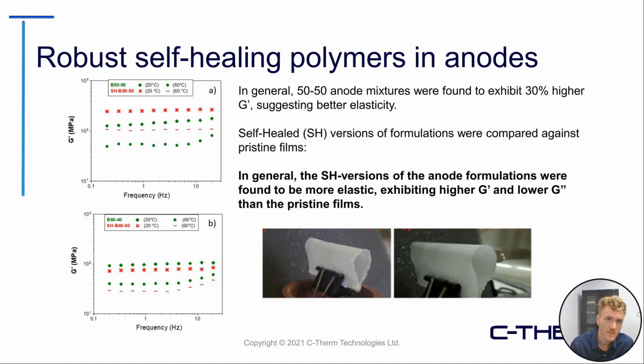And they were able to do some DMA testing by sweeping the frequency and measuring the G prime, or the elastic modulus, during the experimentation. Upon taking some pristine samples of the materials, they found that they had an elastic modulus that was pretty decent, around, I believe, 100 megapascals.